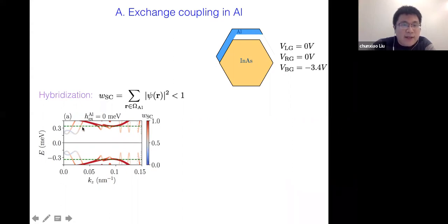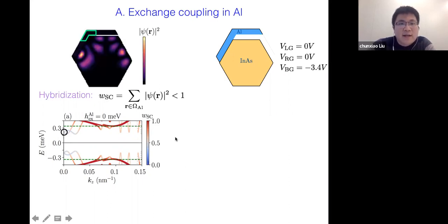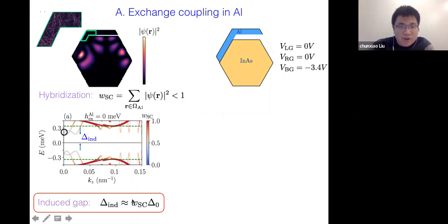So this is actually a spin orbit coupled band for the hybrid state, because its weight is about half. If we look at the wave function of that particular state, we see that about half of its wave function is inside indium arsenide, and half of the wave function is inside aluminum. So in this sense, this hybrid state is induced with a finite superconducting gap, delta induced. I guess this can answer the first question asked before. So in our treatment, this proximity induced gap naturally appears for the hybrid state, and its value is proportional to the weight of its wave function in the superconductor.